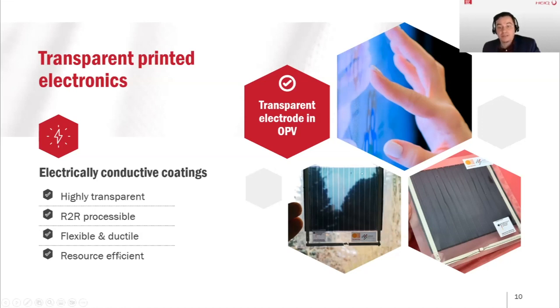One important point is the resource efficiency. For example, for a target conductivity of 100 ohms per square with 10 gram silver wires, you can coat more than 200 square meters of polymer film. So it's a very resource efficient material. And it's also flexible. So if you bend, for example, the polymer film and relax it, you will not lose conductivity. The conductivity remains because the silver wires are very tiny and ductile structures.